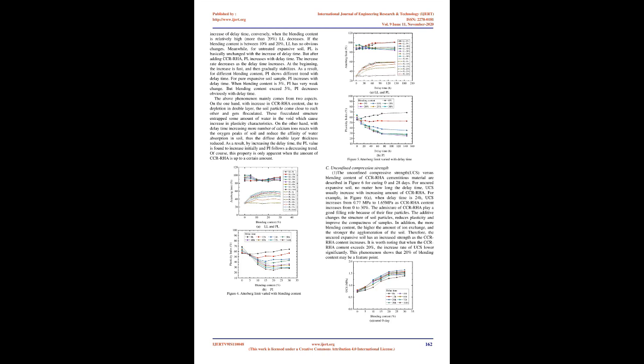For the case of delay and no delay, the change in PL presents two different laws. If there is no delay, immediate compaction, the PL remains basically unchanged even if blending content increases. However, if compaction is delayed, the PL increases first and then decreases with the increase of blending content. The maximum plastic limit point is about 15 to 25%. The trend of LL and PL leads to the following rule of plasticity index. For undelayed samples, the PI increases with blending content, probably because the particle fineness of RHA and CCR is smaller than that of expansive soil. For the samples with compaction delay, with the increase of blending content, the PI decreases first and then increases slowly. Most of the samples reach a minimum plasticity index when the blending content is between 15% and 25%.